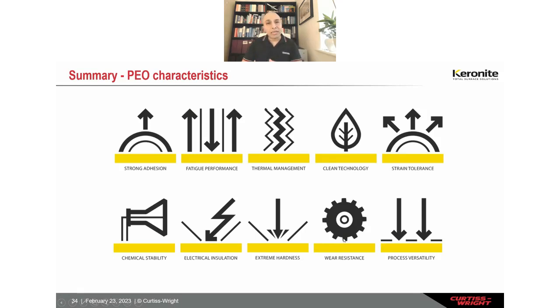And the most important thing is the process versatility. You can coat highly complex shapes. For example, this one, you can coat a tiny titanium bolt just on the surface, only the top landing you can coat, right? You can see, for example, a space baffle here, you can see those coated, even those tiny, tiny pinholes, that needs to have very low optical reflectance. And you can also locally mask it very easily where you need these masked zones for electrical grounding purposes.